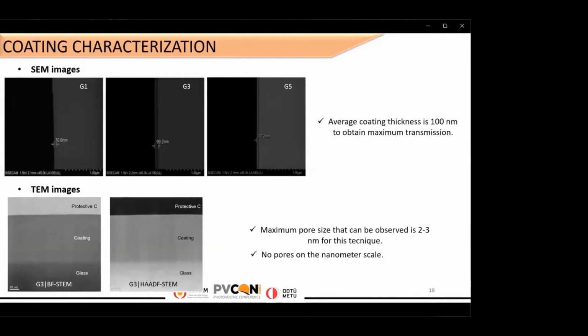Here are the cross-section SEM images of G1, G3, and G5 samples and TEM images of the G3 sample. We have obtained the maximum transmission value with the G3 sample, and its coating thickness is about 100 nanometers. It's also shown in the TEM images that the G3 sample has no porosity at nanometer scale.